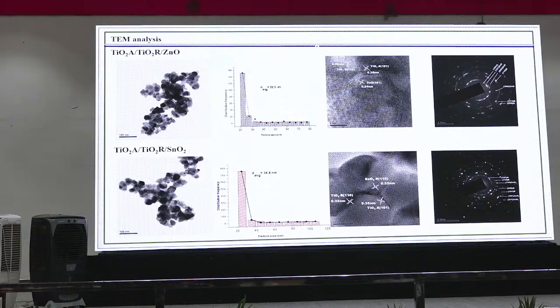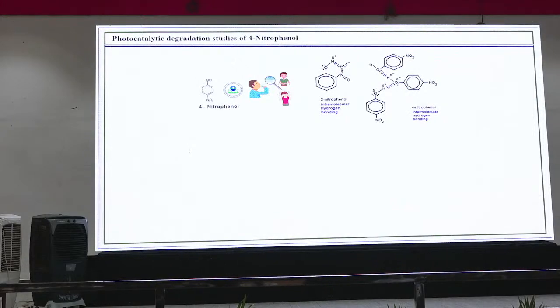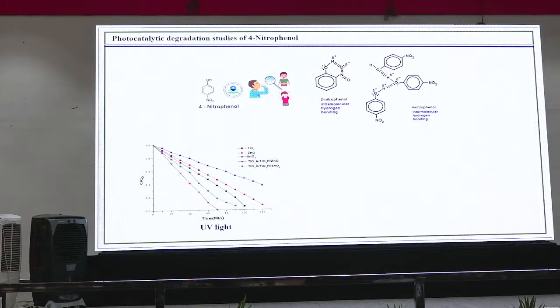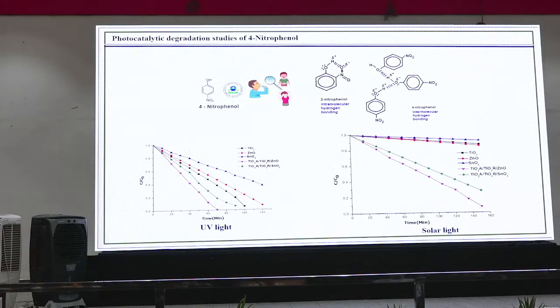So we concluded the heterojunction is formed. Then we wanted to go for the photocatalysis study, so we have selected para-nitrophenol. Para-nitrophenol is very difficult to break compared to 2-nitrophenol, because it has two kinds of hydrogen bonding, intra and inter-hydrogen bonding. When we did that under UV light and solar light, it gave a better result in both UV and solar light.